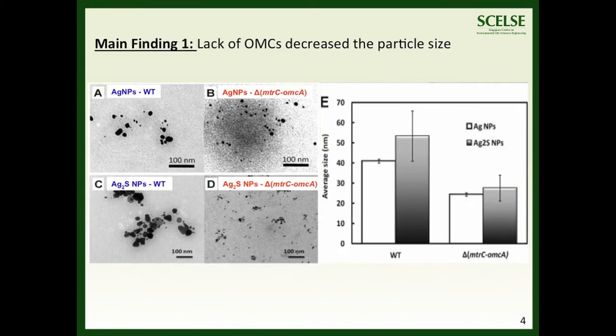We found that the size of extracellular nanoparticles was correlated with the presence of Outer Membrane C-Type Cytochromes on Shewanella oneidensis, where a lack of cytochromes resulted in smaller nanoparticles.